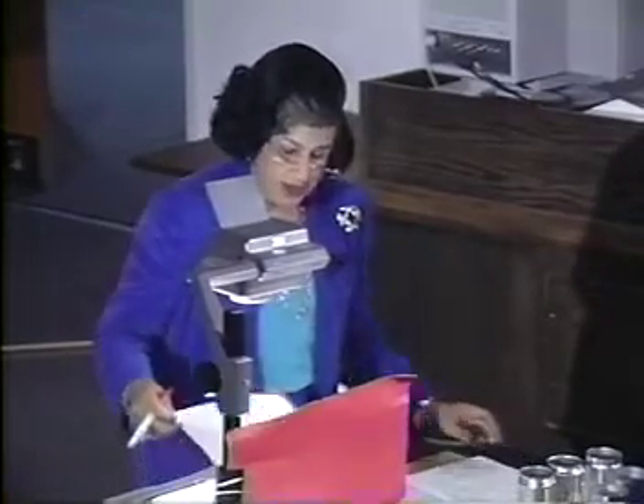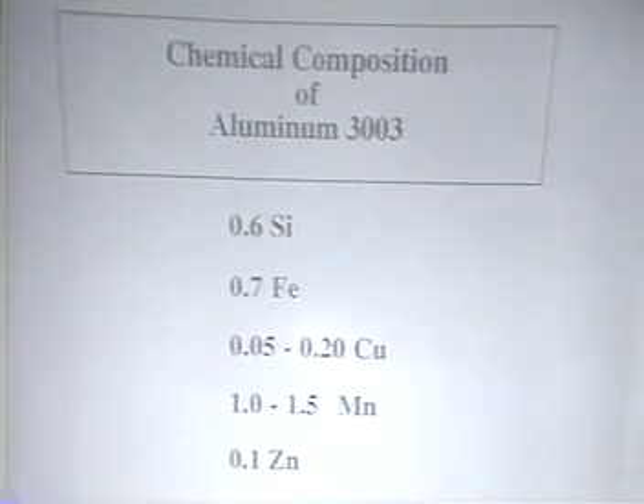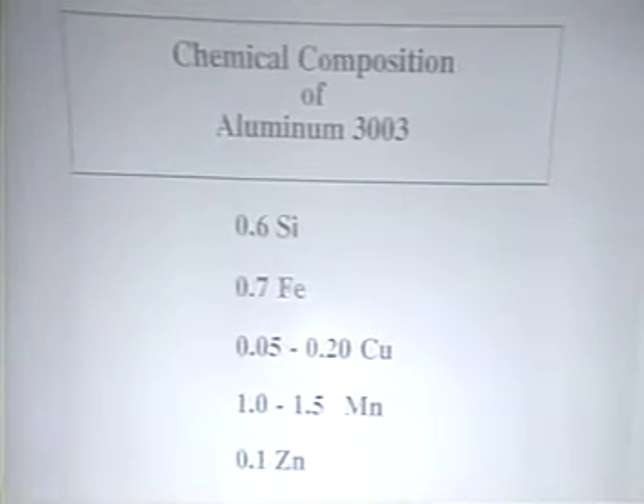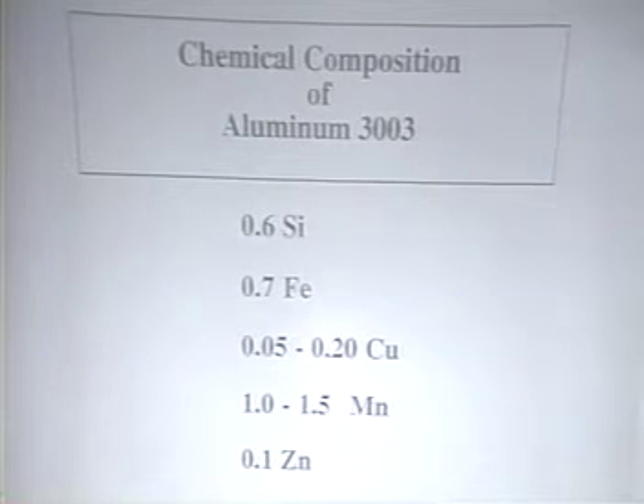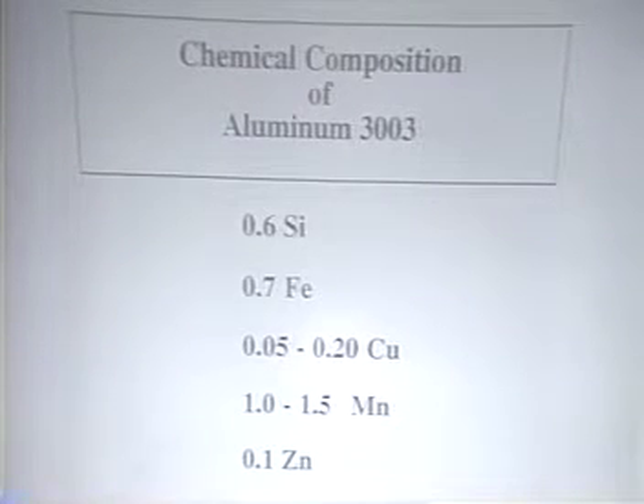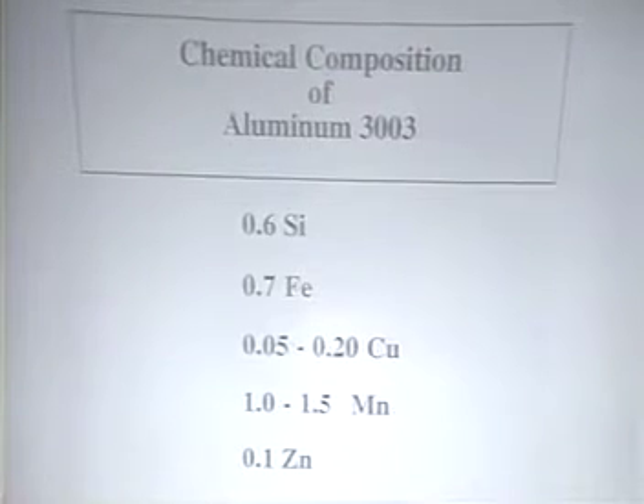Okay, now, in the manufacture of beverage cans, we're looking at aluminum alloy 3003. And this is what it looks like in terms of composition. Just a little bit of silicon, a little bit of iron all the time, trace amounts of copper. The major alloying agent is manganese with from 1.0 to 1.5%.